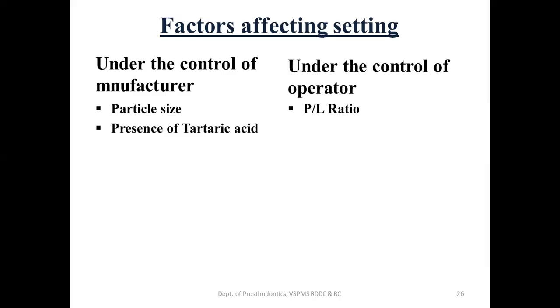Now, what is under the control of the operator? That is the powder liquid ratio and the temperature of the glass slab. Cooler the glass slab, setting time will be increased. Higher the powder liquid ratio, setting time will be faster.